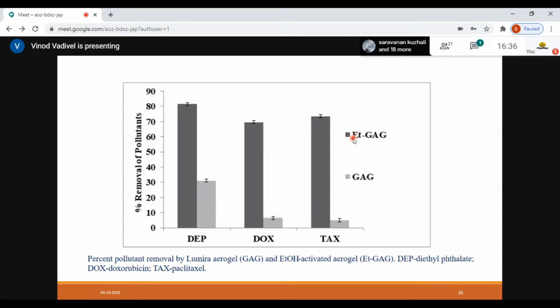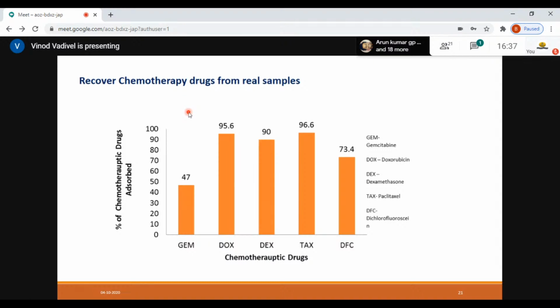But if you activate the system, and by activate I mean just flush the aerogel with ethanol, the removal of pollutants is high. The theme behind this was that you first have a hydrophobic aerogel, and you need to activate the functional groups present on its surface to selectively adsorb these micropollutants. We also studied different chemotherapeutic drugs for real samples.